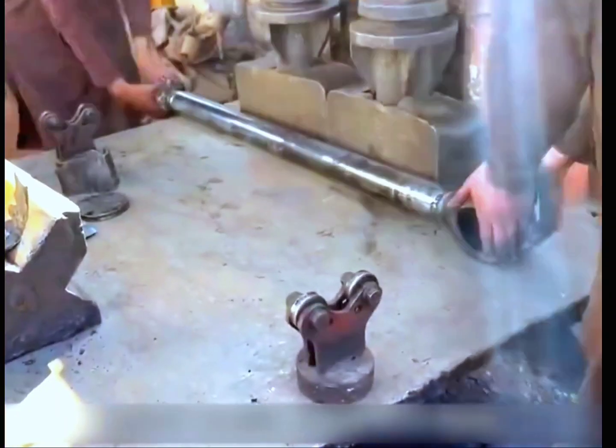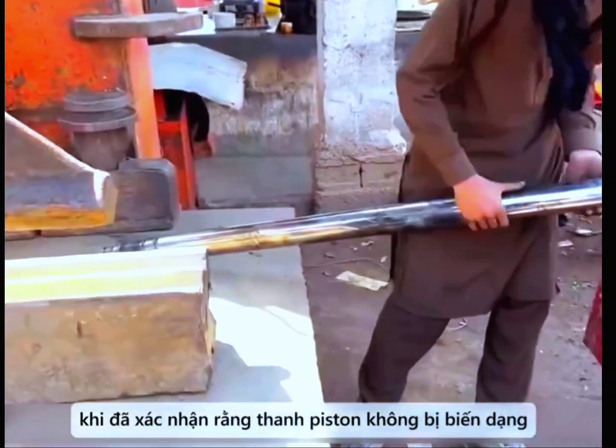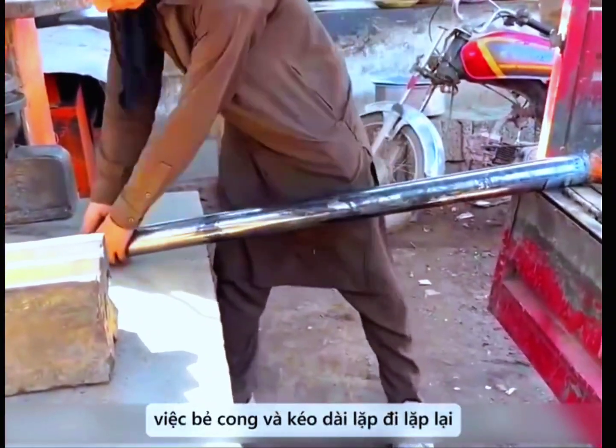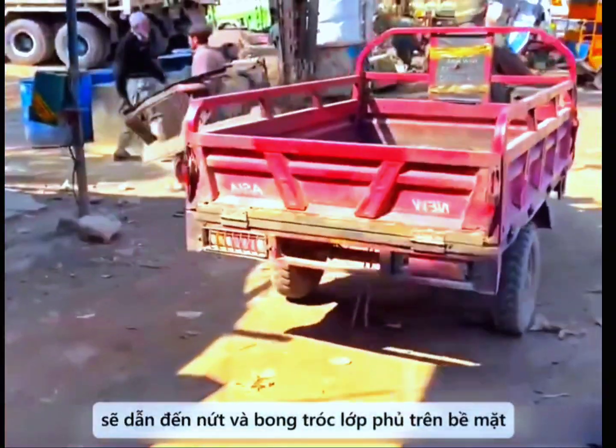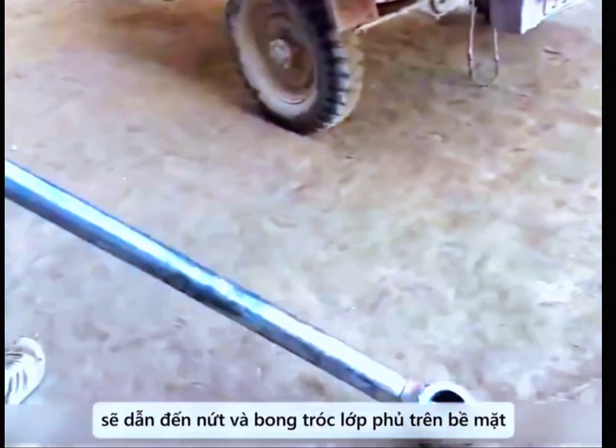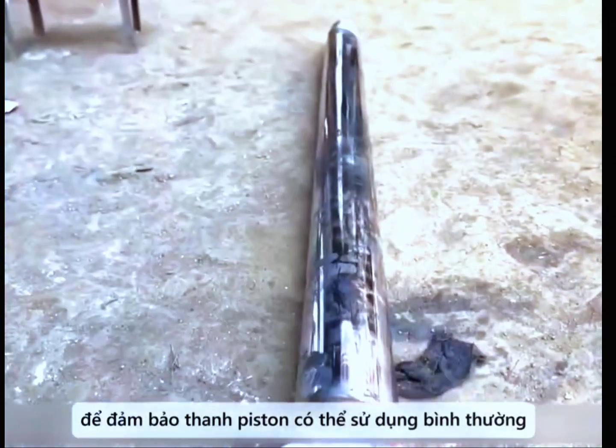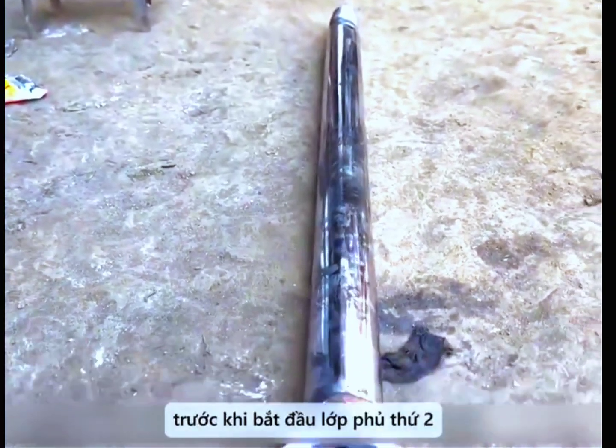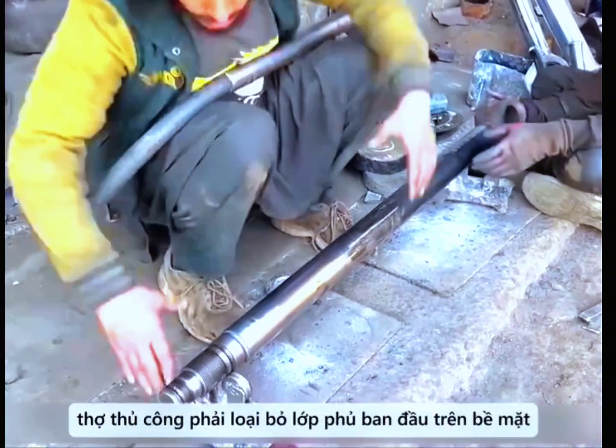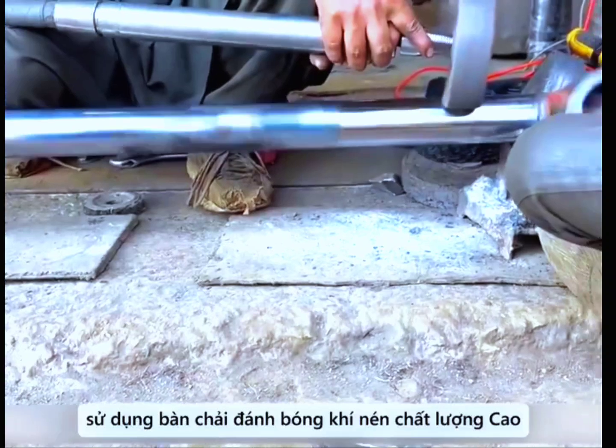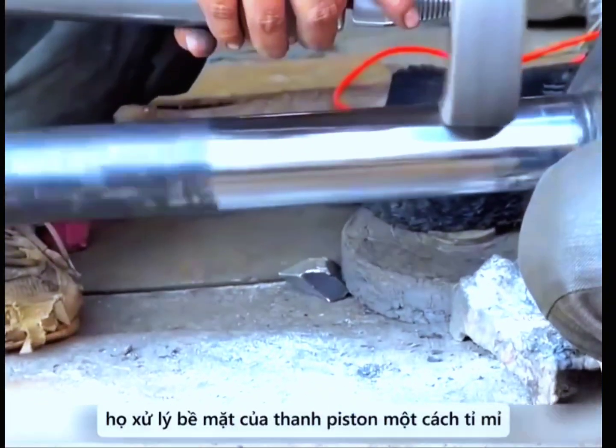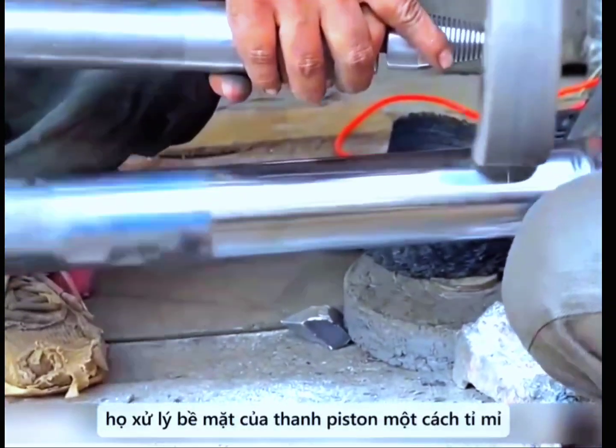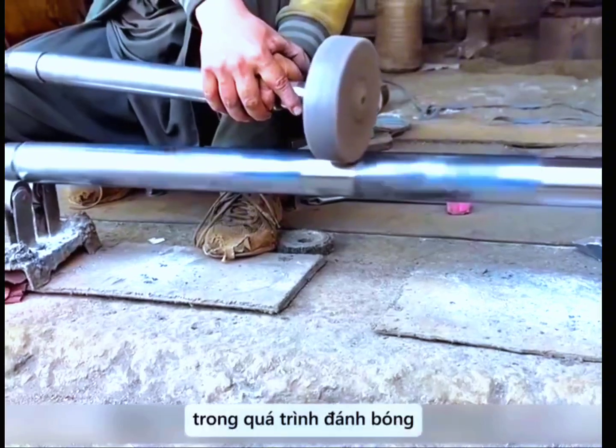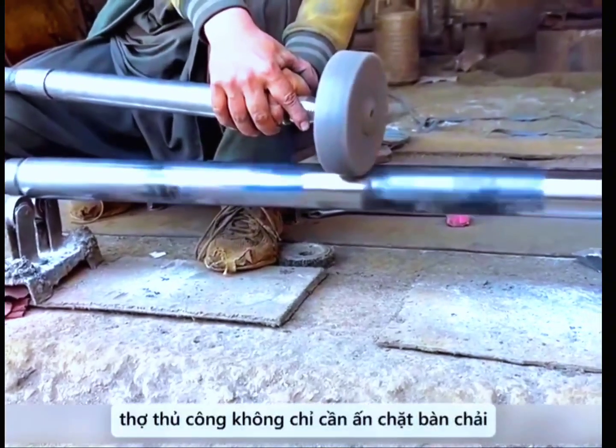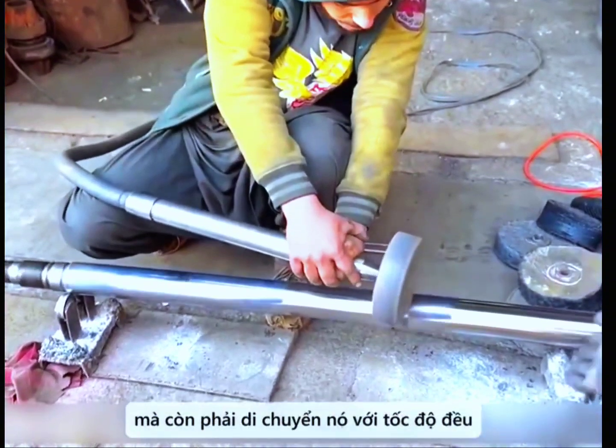In order to ensure that the piston rod can be used normally, the craftsman must remove the original coating on the surface before starting the second coating. Using a high-quality compressed polishing brush, they meticulously treat the surface of the piston rod. During the polishing process, the craftsman not only needs to press the brush firmly, but also moves it at a steady speed. This not only removes impurities from burning and heat, but also makes it easy for the craftsman to check the surface.